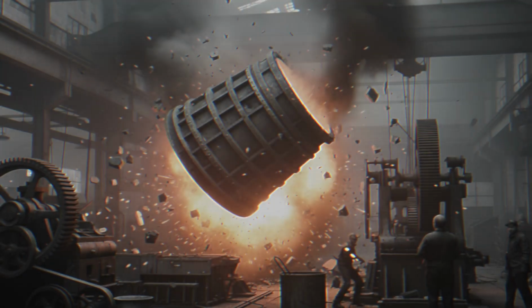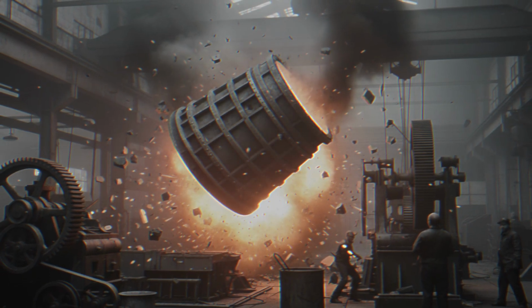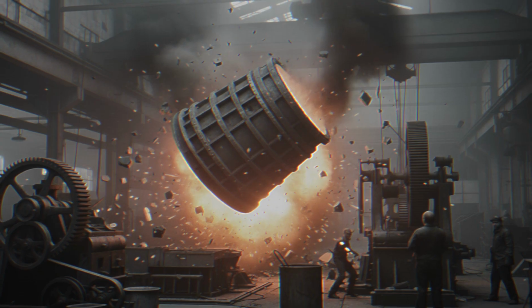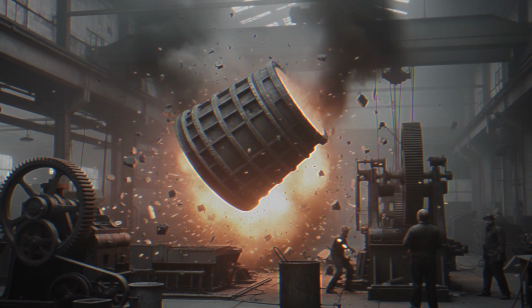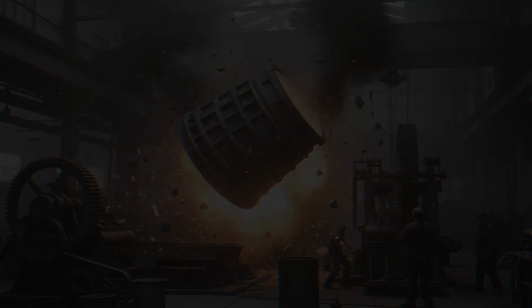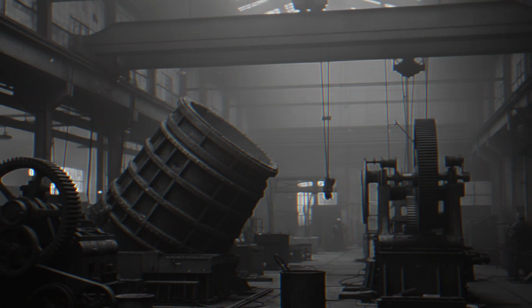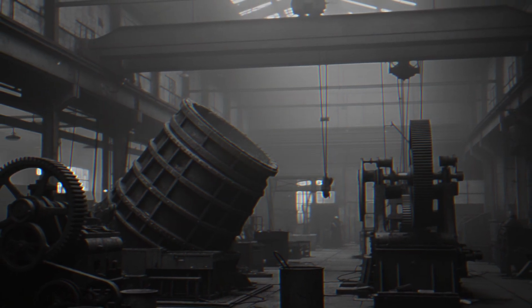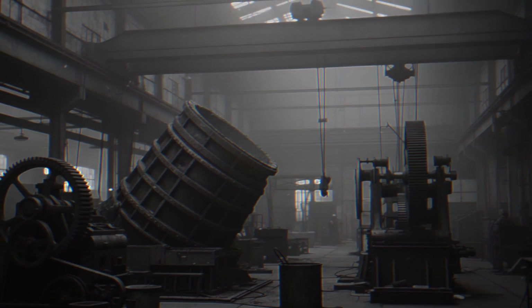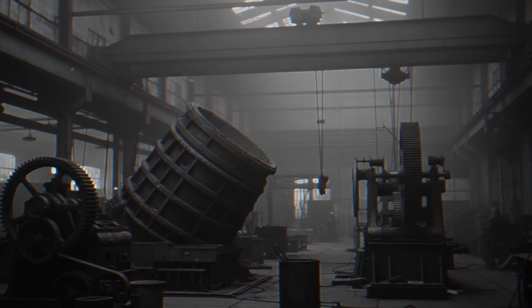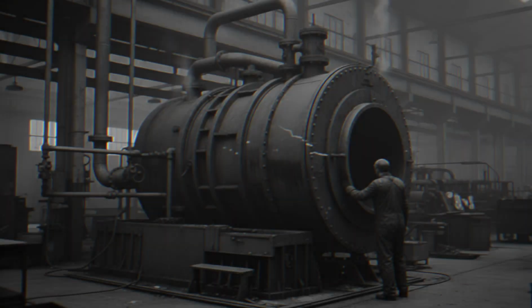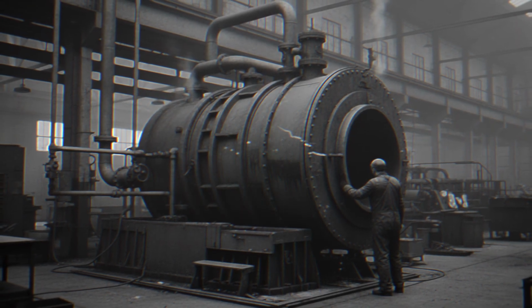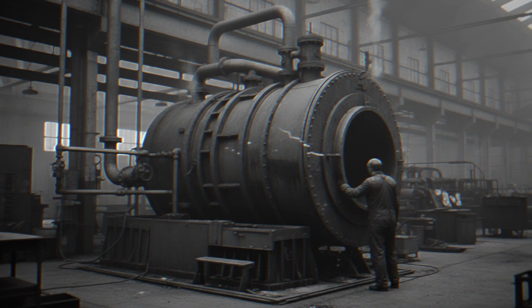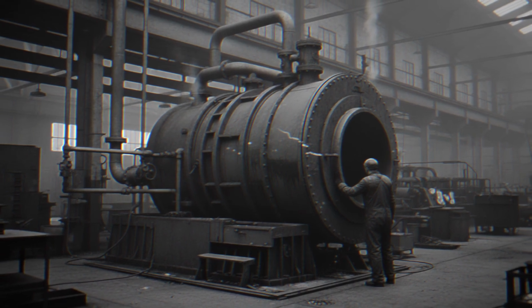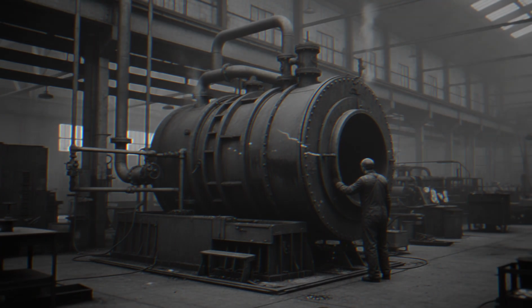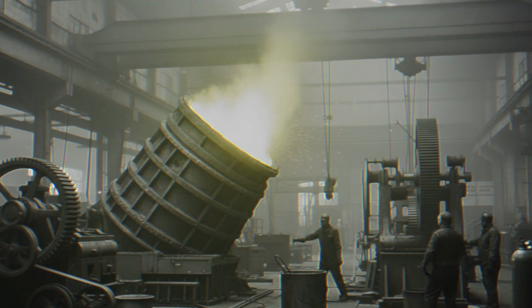The refractory lining, the fire brick and castable ceramic material that separated the iron-bearing burden and the 1400-degree combustion gas from the steel shell of the furnace, wore continuously. During operation, the thermal cycling of each working day expanded and contracted the lining materials differentially, creating micro-cracks that accumulated over time. The abrasive action of the descending burden material, the coke, ore, and limestone charge moving slowly downward under gravity as the iron reduced and sank, eroded the lining from the inside.